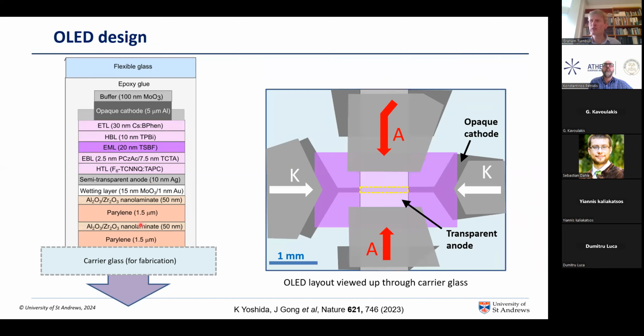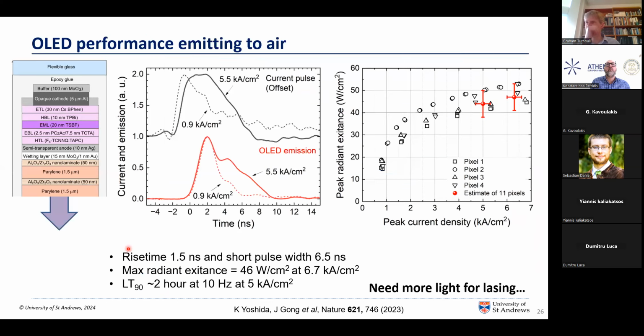We fabricate this whole device on a carrier glass sitting on top of a thin film barrier layer structure. We detach the whole device, which is only about 5 microns thick in total, maybe 10 microns, off the carrier glass, and then place that onto the laser. This shows the OLED performance, where we're driving with few nanosecond pulses of current, and we're getting light emission of up to about 45 watts per square centimeter from the surface of the OLED.